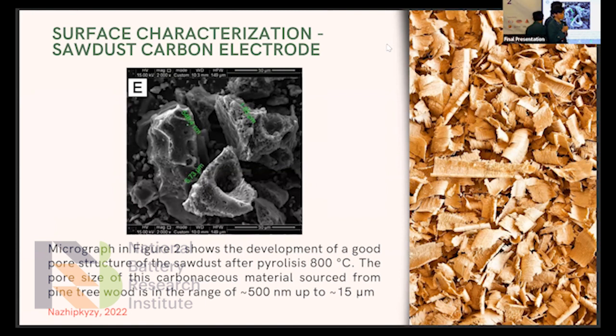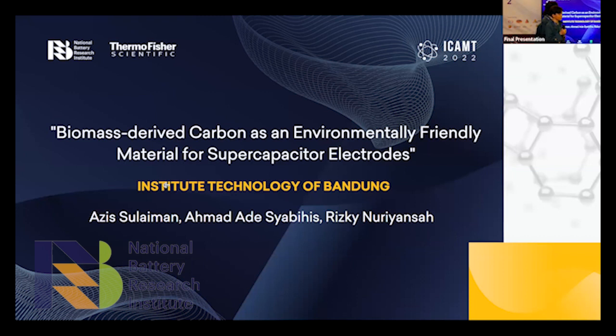Yes. So do you measure the carbon content in your material? Because I know that you have done this pyrolysis, but the composition of the carbon I think is not pure, perhaps 85% or 95%. So the purity of the carbon, because your carbon will be used for the capacitor, right? Okay, so in fabricating the carbon electrodes, we combine our carbonaceous materials from the sawdust and the activated carbon that we have in our laboratories from the coconut shells. So the ratio is 4 carbonaceous materials and 1 activated carbon from coconut shells.